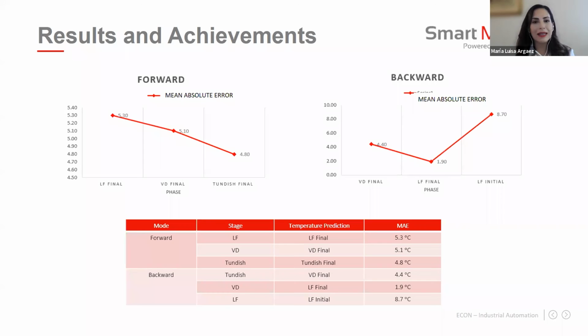By selecting the best parameters and the best data science models with the forward model, we obtain the final temperature estimation in the ladle furnace, in the VD, and at the tundish with a mean absolute error of 5.3, 5.1, and 4.8 Celsius degrees respectively. And with the backward modality, we obtain the final temperature estimation in the VD and in the ladle furnace with a mean absolute error of 4.4 and 1.9 Celsius degrees respectively. And the initial temperature in the ladle furnace with a mean absolute error of 8.7 Celsius degrees.